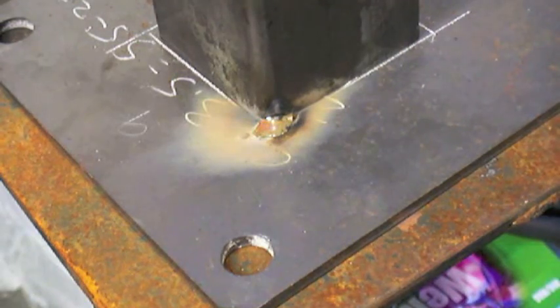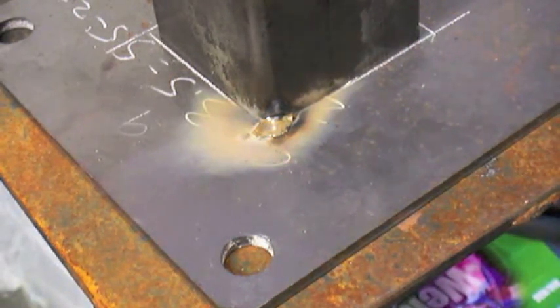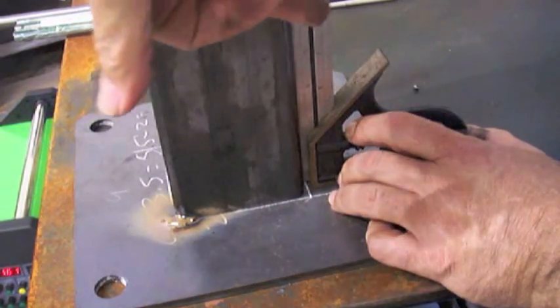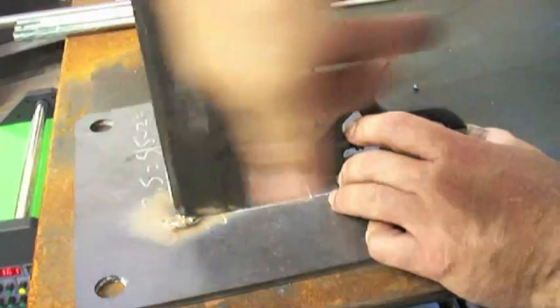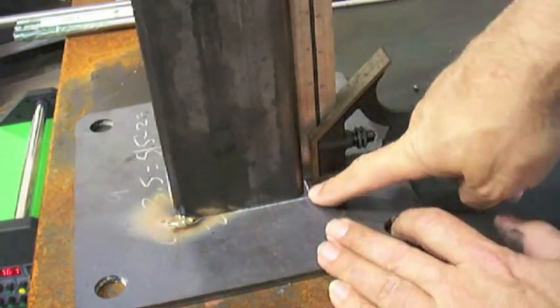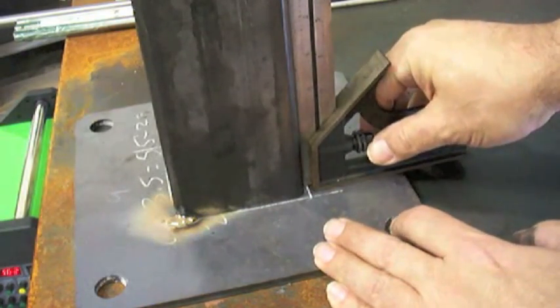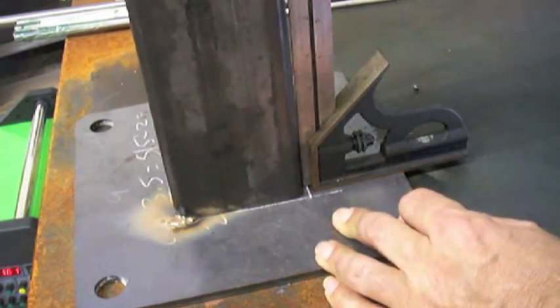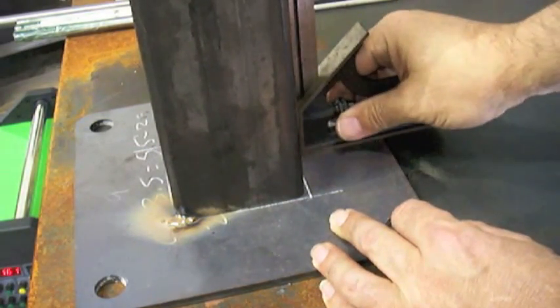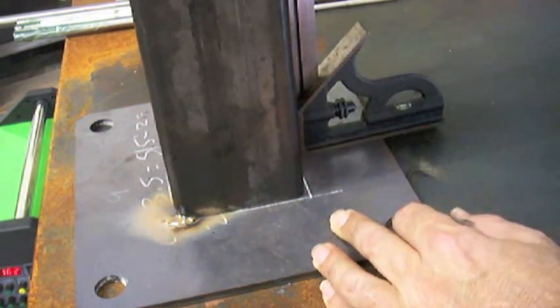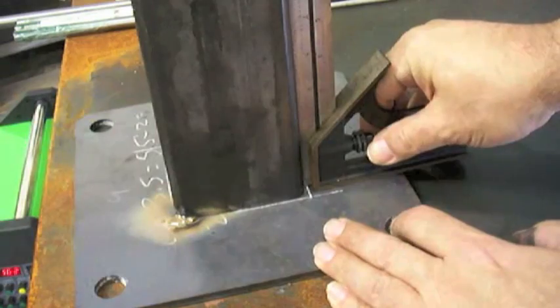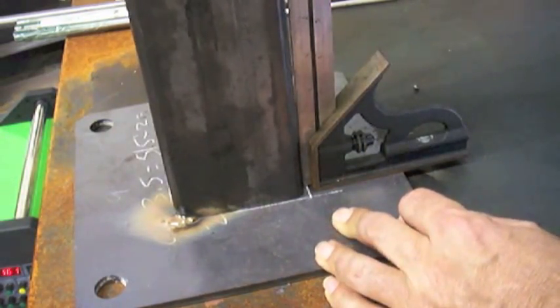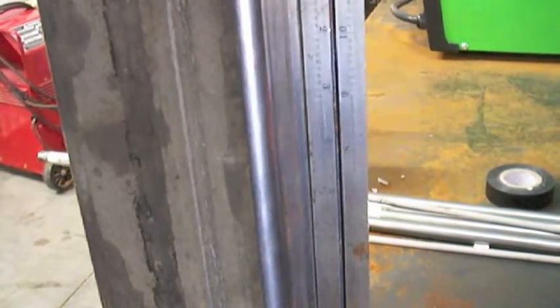From there, you have to get this thing square one direction at a time. Going to my right, I'm going to bump this thing around. I know that when I put the tack on the corner, shrinkage stress of that weld metal is going to pull it down. It's going to pull a lot more than you think sometimes. So I'm going to bump this around to where I get roughly about a 1/16th of an inch out of square to the top of that 12-inch blade.